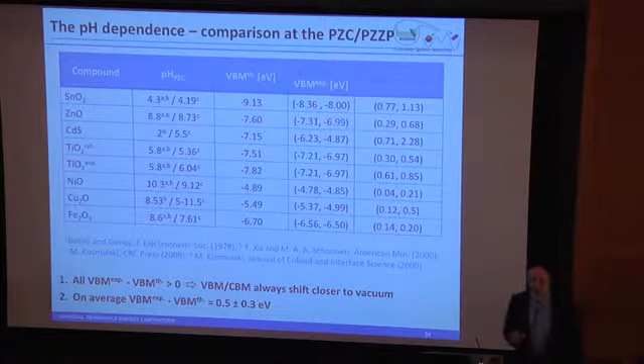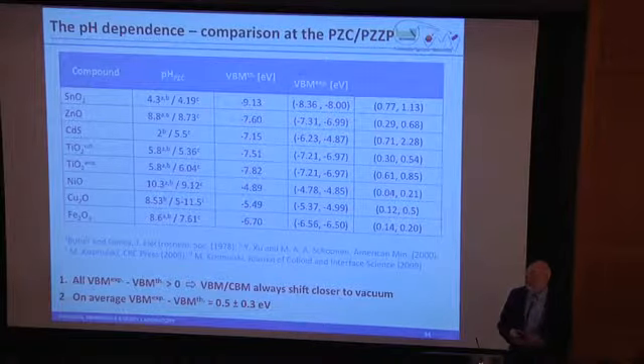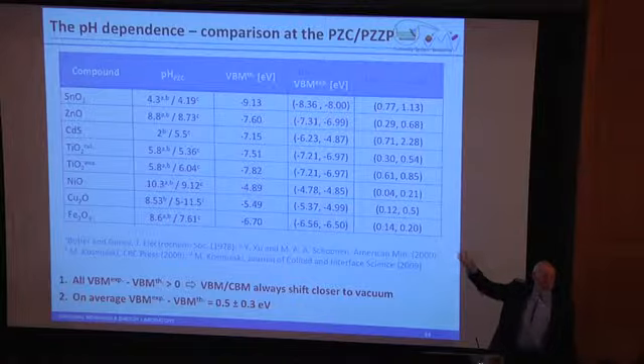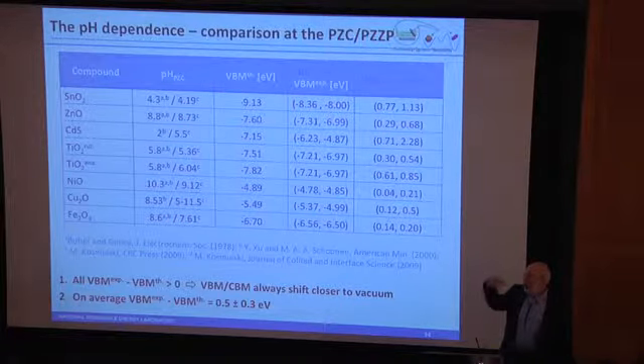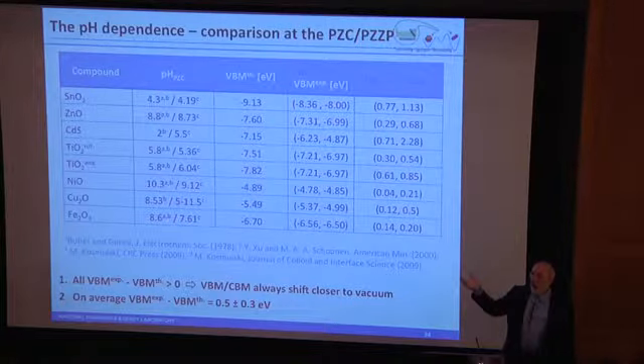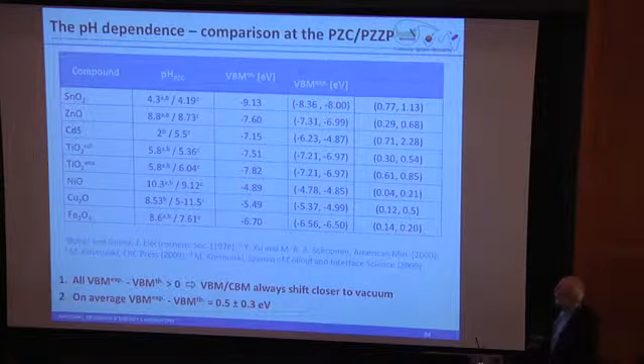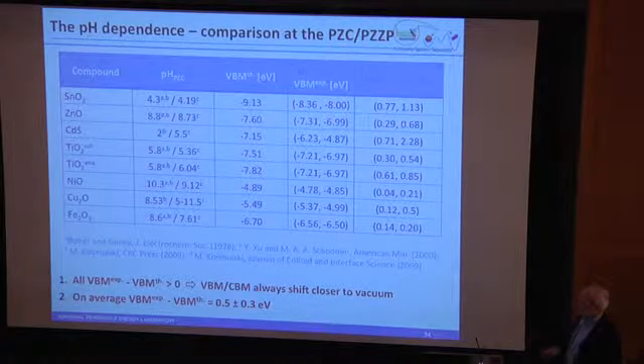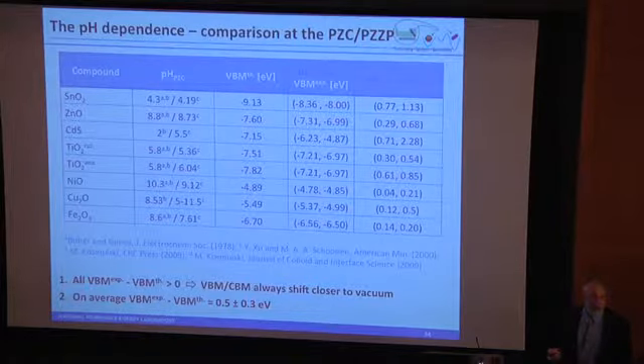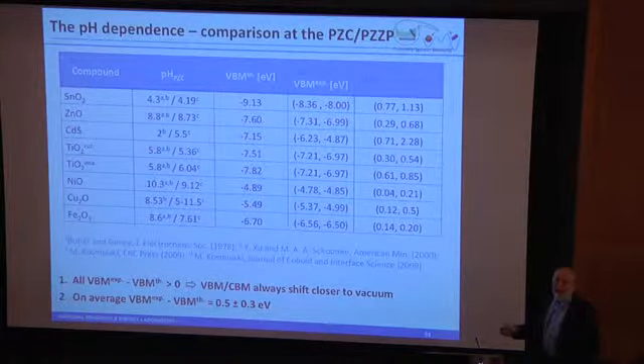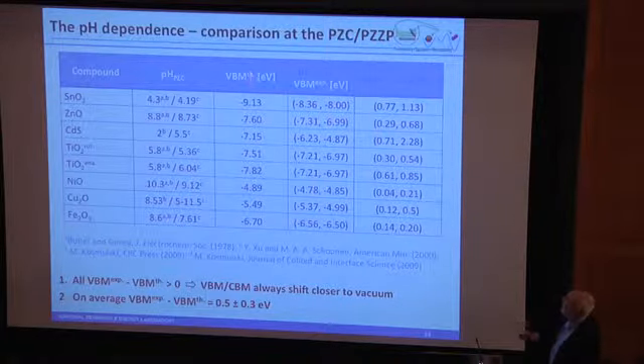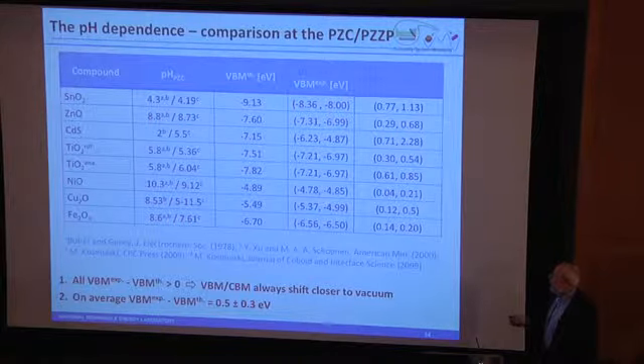The point of zero charge is very important technologically because it drives how you make latex paint, for example. How do you suspend the nanoparticles of TiO2 in the paint so they don't agglomerate? It has a lot to do with the point of zero charge. So DuPont is very interested in it. Dow's very interested in it. But they don't publish tables of the point of zero charge for different materials. And so one of the challenges here is we have to go measure a whole lot more of these to make sure we're accurate, because if we're not accurate, then our 0.5 volts might not actually be right. And you can see that there's a pretty good variance in what the reported PZC is for these materials. And so it's important that we get better measurements.